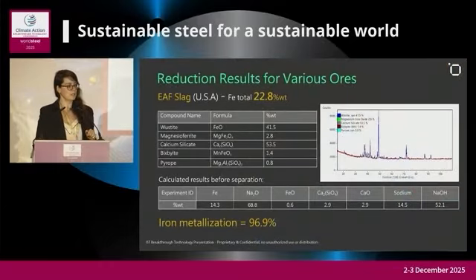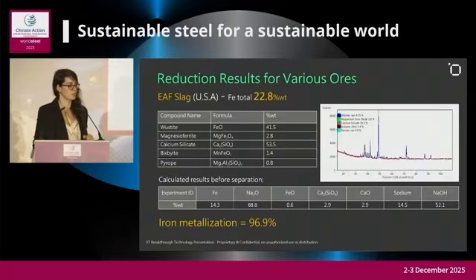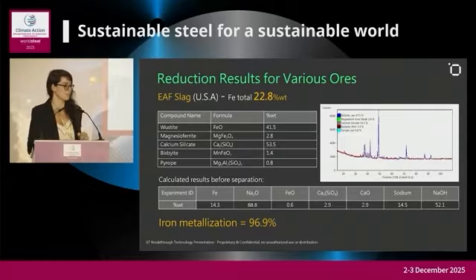So you can see here in the XRD before and after the metallization percentage. We've reached 96.9% of metallization. Most of the iron-bearing phases turned into iron metal. Again, 96.9%. The Fe total in the raw material is only 22.8%. And it's really a challenging material to deal with due to the calcium silicate inside and the other compositions.